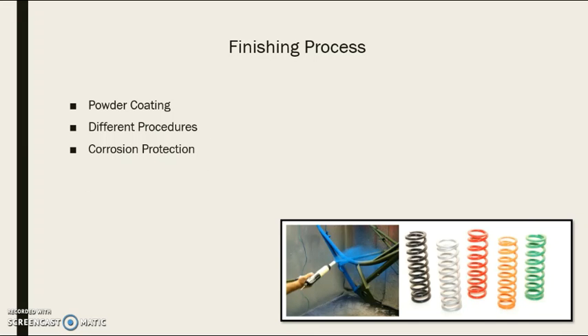Suspension springs in the car are protected from rust, corrosion, and scratches by a type of powder coating. This is the finishing process that the springs ultimately go through. So in order to apply this coating, the base material must first be prepared by cleaning it. Then the metal is dipped into an acid, and this process is called phosphate coating. There are three main types of this: manganese phosphate coating, zinc phosphate coating, and heat-stable zinc phosphate coating.